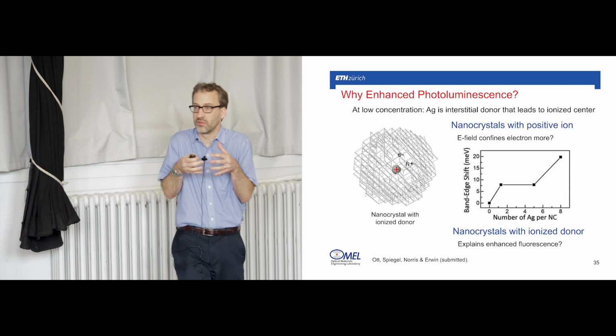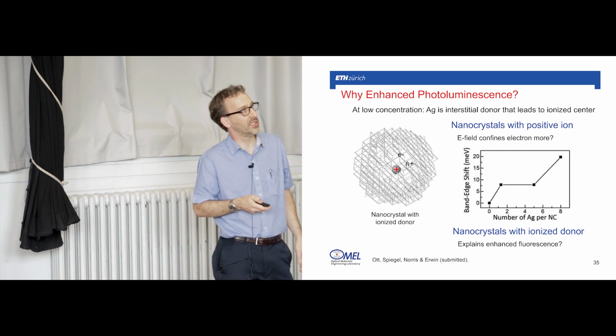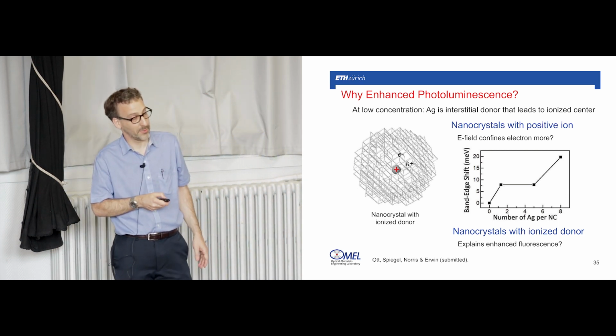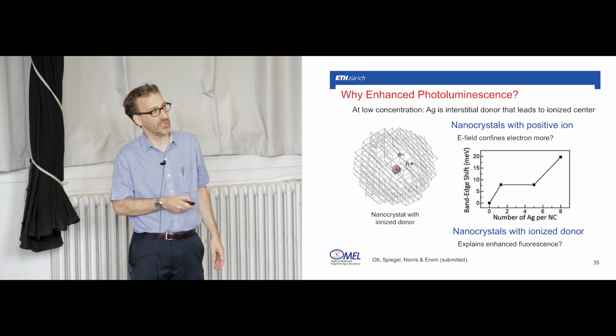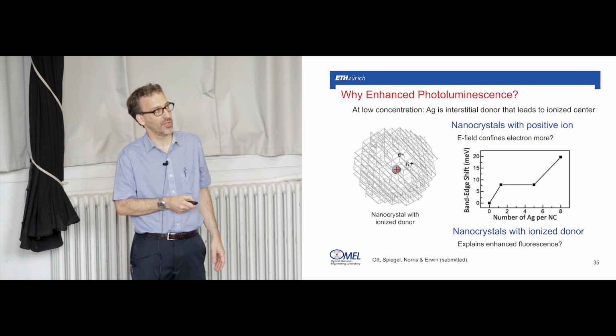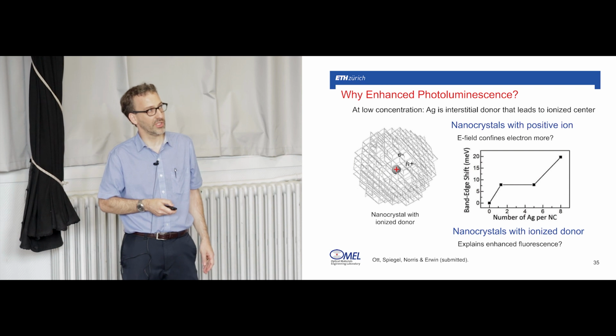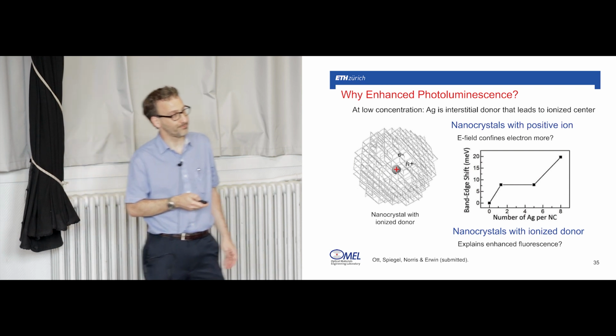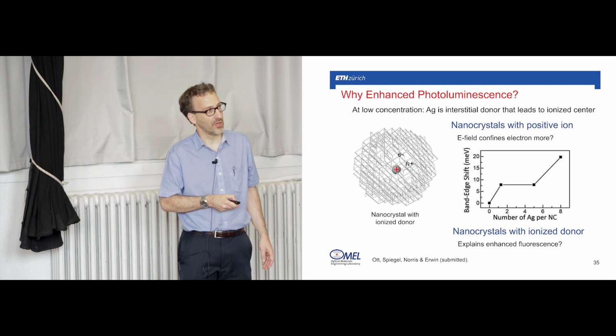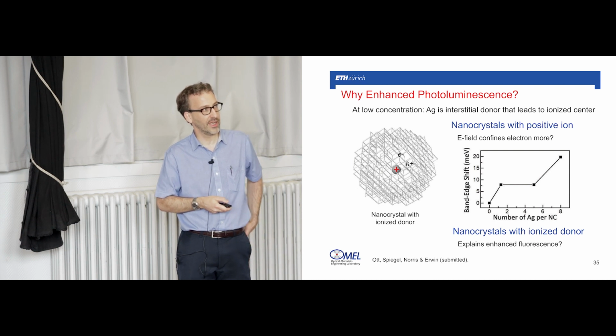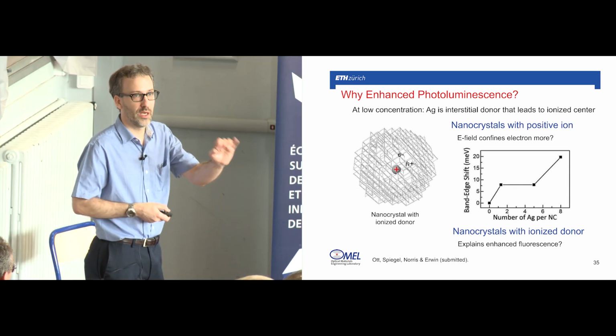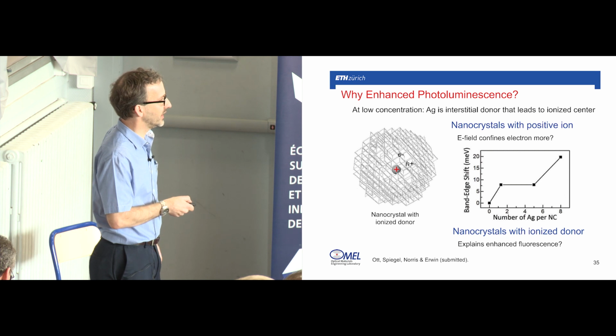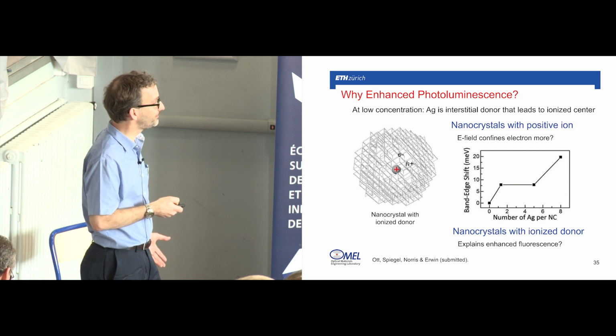This would be consistent if the electric field of this positive cation confines the electron a little bit more. If that's really going on, we should see a blue shift in the photoluminescence, and that's exactly what we see. Even adding 1 silver on average, we see a clear blue shift in the photoluminescence of the particles. So all of this seems to suggest that an ionized donor, a kind of ionic doping, can be something interesting that enhances the fluorescence.